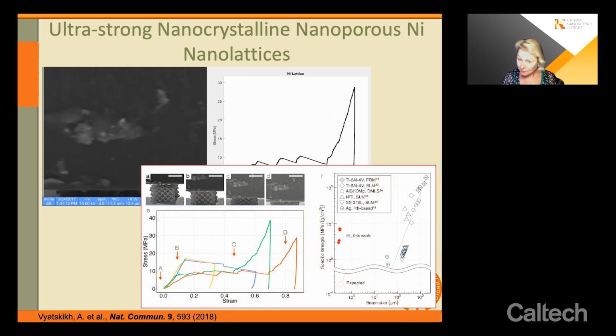So at that time, we plotted here the specific strength of many, many different metals. So what I mean by specific strength is the strength normalized by density, so that we can compare across multiple different metals. And we're plotting this as a function of their dimensions. So what you can see is that the additive manufacturing routes that exist today, the strength drops off dramatically as you reduce the dimensions by simply a factor of 10. So when you go from 1 millimeter features to 100 micron features, you can see that they lose about 2 orders of magnitude, actually more, in their strength.